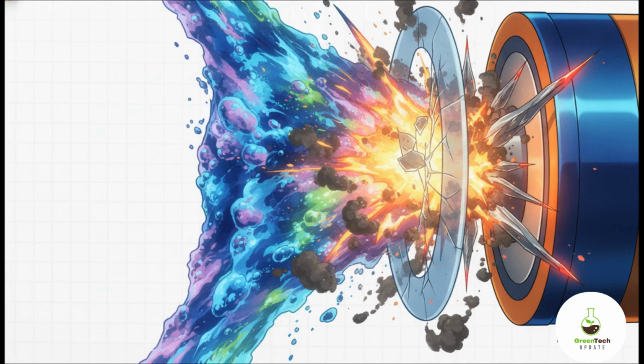So you might be wondering, why aren't they everywhere? Well, that brings us to the liquid problem. Traditional batteries use liquid electrolytes to slosh ions back and forth, but calcium and zinc are highly reactive. When you pair them with standard liquid electrolytes, they immediately trigger all these unwanted side reactions. The result? You get these thick, crusty, passivating layers and sharp metal spikes, they're called dendrites, that basically grow and literally pierce and kill the battery right from the inside out.